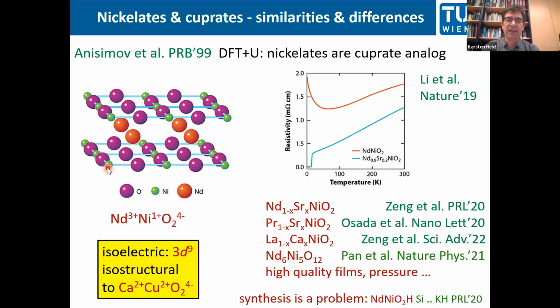So you have a nickel oxygen 2 plane, then you have here a neodymium buffer layer before you have the other nickel oxygen 2 layer. So that very much reminds of the cuprates. It's even the very same crystal structure as one cuprate. And since nickel is neighboring copper in the periodic table, but if you take a trivalent instead of a divalent cation here, you end up, in a formal valency count, in the same 3d9 electronic configuration. So that is very similar.